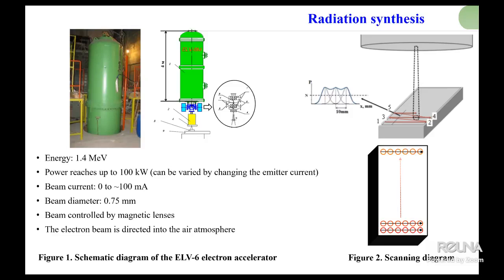The electron beam was deflected in one plane at a frequency of 50 Hz, while the target was moved perpendicular to the beam at a speed of 10 millimeters per second. This configuration allowed for uniform irradiation of samples. In practice, each point of the surface was exposed to a short electron pulse with a duration of about a millisecond. And due to scanning, a uniform dose distribution over the entire sample area was achieved.